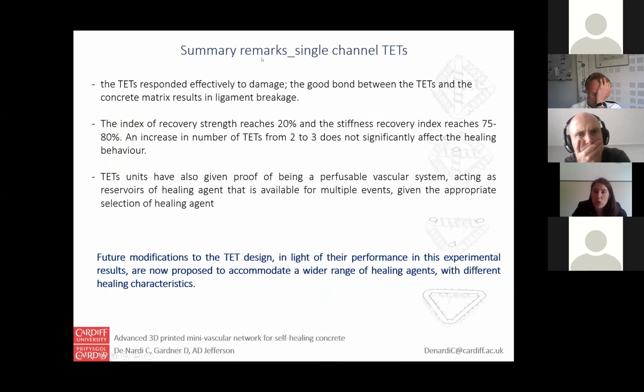So if we have to remark something, well, actually this system responded effectively to the damage. We have a good bond between the TETs and the concrete. It appears to have a kind of ceiling value in terms of strength and stiffness. So we reached 20% in terms of strength and 75–80% in terms of stiffness. And the number of TETs seems not to really affect the healing behavior. So this system is good for perfusible healing behavior and is available for multiple events, if we give the appropriate selection of the healing agents.